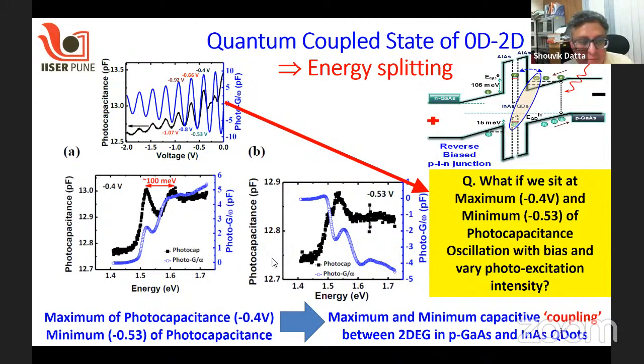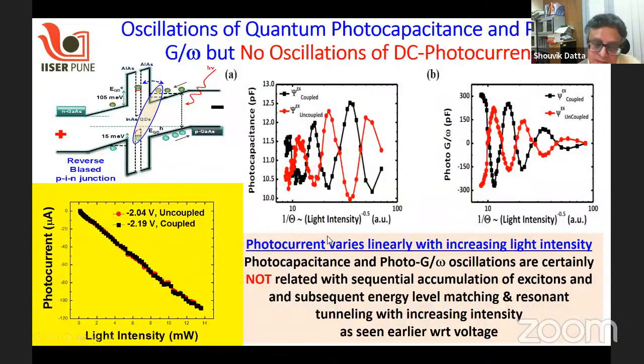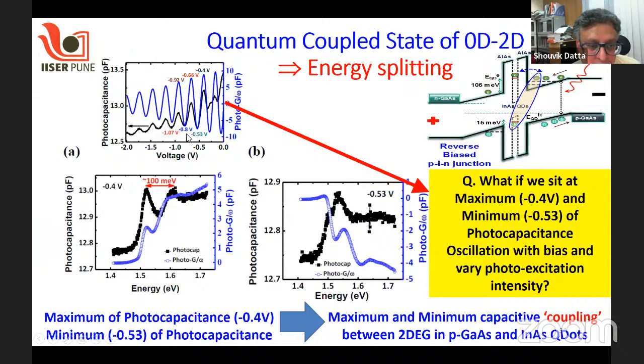So just quickly telling you a very interesting result: we again thought of sitting at the bias voltages of these maxima and minima and then trying to vary the light intensity. This result is still unpublished. We had actually overlooked the behavior of photocurrent for quite a long time. Once we are sitting at one particular bias voltage, that is pinning the energy levels, and there are no oscillations in the photocurrent. But if you look at the behavior of both photogenerated capacitance and photoconductance, you see very interesting oscillations. In fact, minus 2.04 and minus 2.19 are one of those oscillation maxima and oscillation minima.